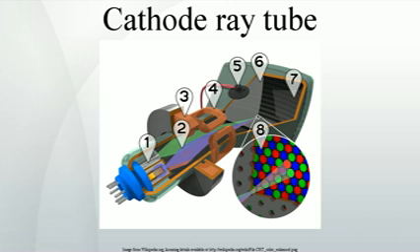While the TCLP process grinds the glass into fine particles in order to expose them to weak acids to test for leachate, intact CRT glass does not leach; the lead is vitrified, contained inside the glass itself, similar to leaded glass crystalware. In October 2001, the United States Environmental Protection Agency created rules stating that CRTs must be brought to special recycling facilities. In November 2002, the EPA began fining companies that disposed of CRTs through landfills or incineration. Regulatory agencies, local and statewide, monitor the disposal of CRTs and other computer equipment. In Europe, disposal of CRT televisions and monitors is covered by the WEEE directive.